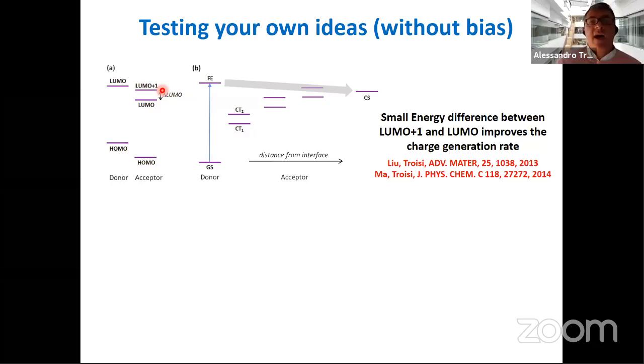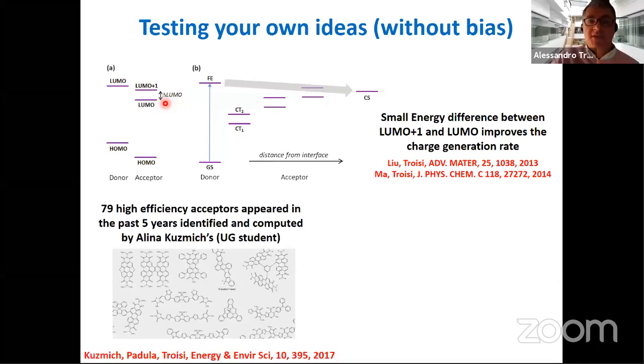What does matter is that now we can actually collect, a few years later, data from the literature to see if the best electron acceptors have these properties. So what we do in this case, when we need to collect data, we resort to undergraduate students, who are particularly cheap for trivial types of activities, and they know more chemistry than most of the people in my group. And so in this case, Alina spent a few weeks looking at the literature and collecting 79 high efficiency acceptors that appear in the literature, and tried to see if there is a correlation between having a small LUMO to LUMO plus 1 gap and having a high efficiency.